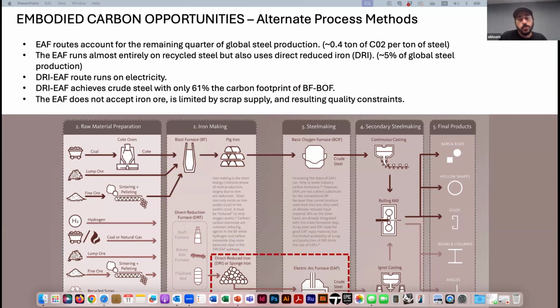And so an alternative to reduce steel's embodied carbon is alternate process methods. The second main alternative is the electric arc furnace, which accounts for about the remaining 1/4 of global steel production. It runs on electricity and can produce just shy of 1/2 ton of CO2 per ton of crude steel it produces. Its main inputs are recycled steel scrap, but it'll also accept direct reduced iron. Direct reduced iron is essentially iron ore chemically stripped of its oxygen within its solid state, skipping the liquefaction that you'd see in the blast furnace, and produces a sort of sponge iron that can then be fed into the electric arc furnace.